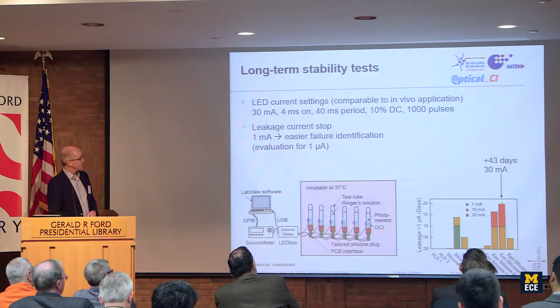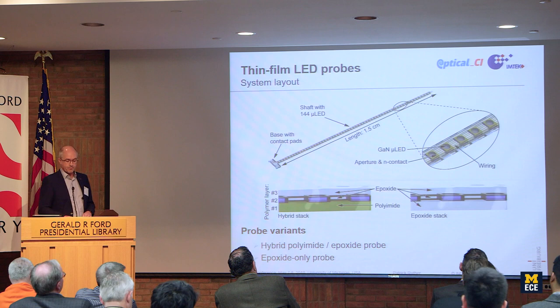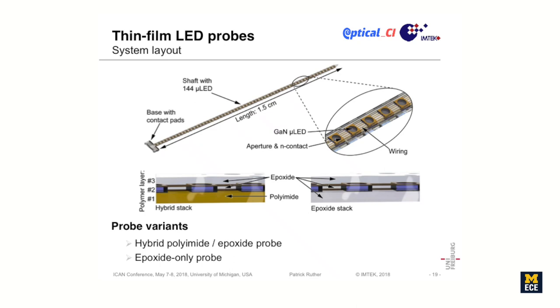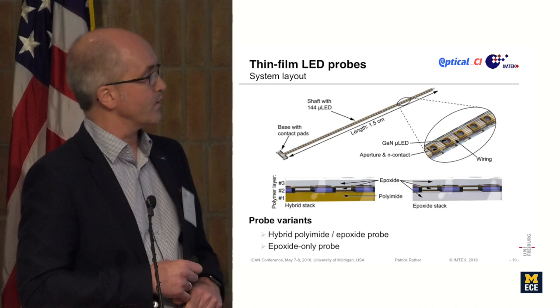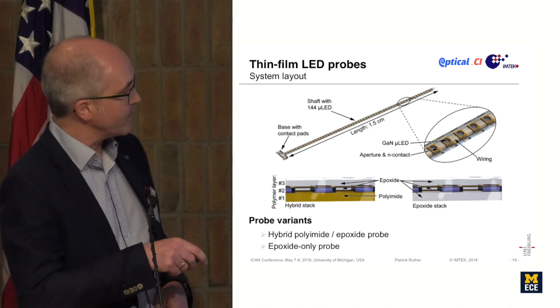Now the second type of probe is something where we do our own thin film LEDs. A bit different from what you do here in Michigan. In our case, we do a wafer level transfer. So we take thin film LEDs and transfer them onto a substrate. The example that you see here is a probe that contains 144 micro LEDs aligned along this 1.5 centimeter long probe shank. We operate them in a multiplexing fashion by 12 plus 12 contact pads.